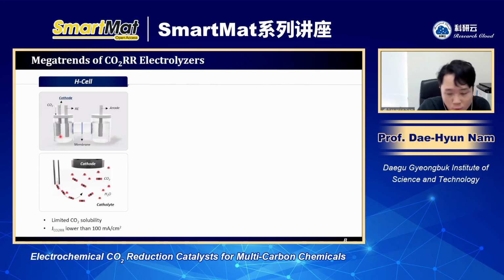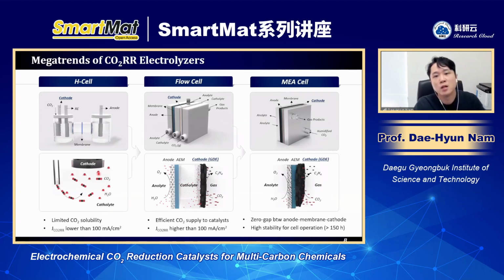So for the CO2 reduction, it means that dissolved CO2 should react within the aqueous electrolyte states. It means that there can be CO2 mass transport limitation when it goes to high current density CO2 reduction. Therefore, people try to develop electrolyzers to enhance the CO2 mass transport. So there is a reason why these days people are doing CO2R using this kind of flow cell or MEA cell.